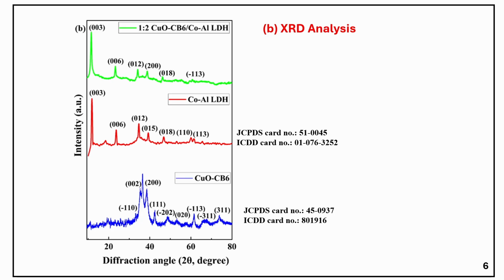Next, coming to XRD analysis. XRD analysis confirmed the successful synthesis and structural properties of the materials. The crystal phase of the CuO nanoparticles was identified using JCPDS and ICDD card numbers, and their monoclinic structure and average crystallite size of 14 nanometer were determined. The cobalt aluminum LDH diffractogram exhibited distinct peaks that were in close agreement with established JCPDS and ICDD card numbers. The XRD pattern of the 1:2 nanocomposite confirmed its formation by showing shifted diffraction peaks compared to the pristine CuO-CB6 and cobalt aluminum LDH, which suggests that CuO-CB6 nanoparticles are confined within the cobalt aluminum LDH structure.